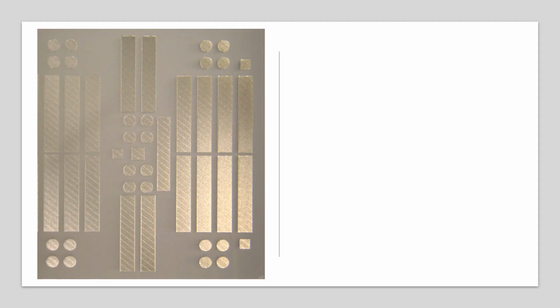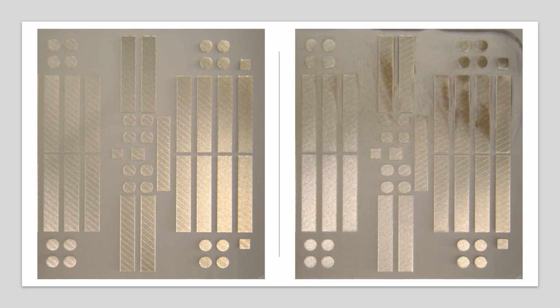Okay, let's just finish up. Remember, we said that maybe 80% of failures are down to support or orientation. I'm going to argue this particular failure is maybe down to orientation. We're necessarily building some tensile bars that are orientated horizontally. At the end of this particular slice, everything looks fine, but on the next slice we can see here something's definitely gone wrong in this corner here. And in fact, what's happened is the bolt in the corner here of the substrate has actually sheared off and caused all of the powder to vibrate up, redistribute itself. So that's a catastrophic failure.